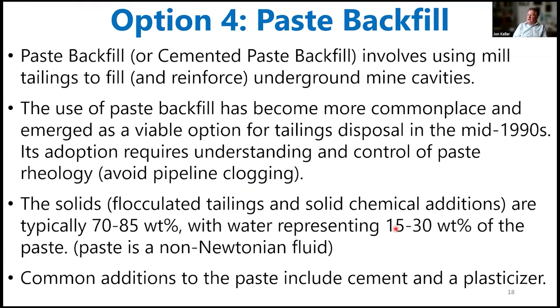Option 4 is paste backfill, or sometimes it's called cemented paste backfill, and it involves taking the mill tailings to serve as a reinforcement for underground mining cavities. And this really emerged in about the 1990s, just as a new technology for tailings disposal. Here, the flocculated tailings and some chemical additions are typically about 70 to 85% solids, with water representing about 15 to 30% of the paste.